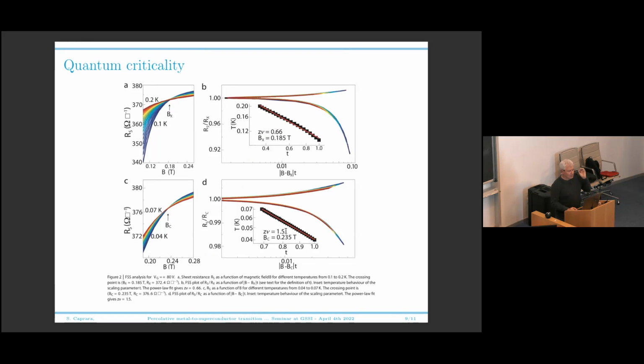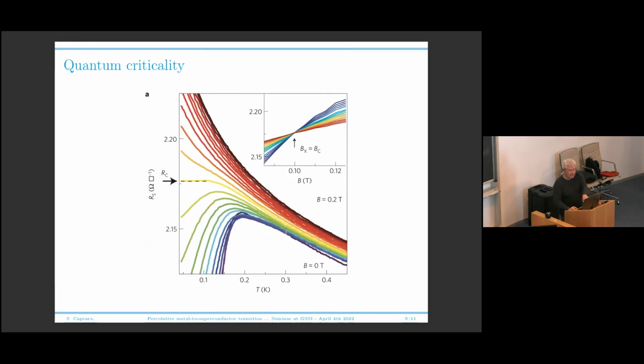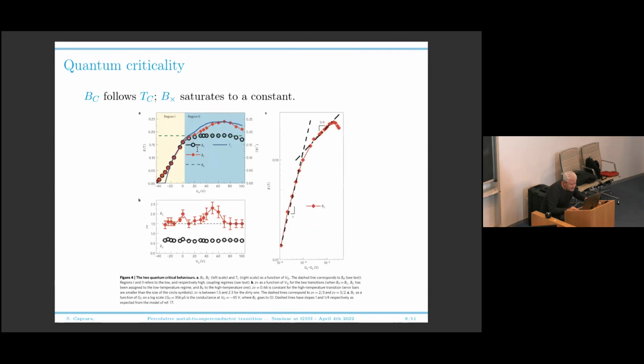And also, when you deplete a lot your two-dimensional electron gas, then BC and B cross come to coincide. This is a situation where the two coincide here. You have only one flat point, but you can follow their evolution. So you go from a situation, I will show you the picture. Maybe this is interesting. This is B cross, the black dots, and this is BC, the red dots. The red BC, the largest of the two when the two are different, scales exactly with the superconducting critical temperature, with a conversion factor that is very convincing, because you convert one Kelvin for one Tesla. For people that deal with superconductivity, this is a very fair conversion factor between magnetic fields and temperature. One Kelvin corresponds to one Tesla.